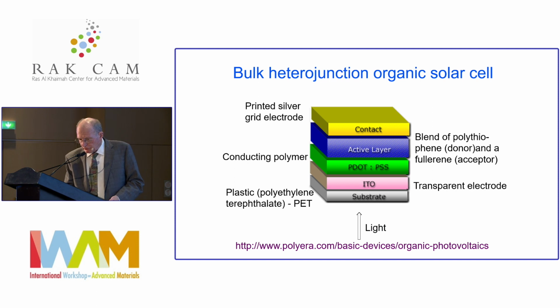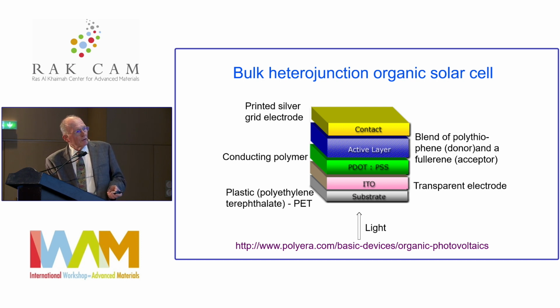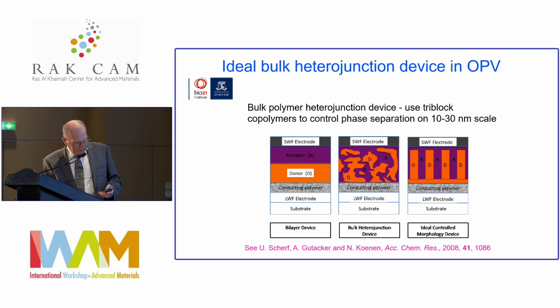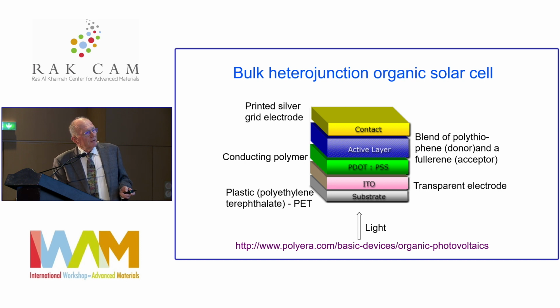Now, the bulk heterojunction solar cell has a typical configuration as illustrated on this slide. This is a simplified version, but you have a conducting positive contact anode, indium tin oxide, a conducting polymer, then the active layer, which in early devices was a blend of a donor polymer such as a polythiophene and an electron accepting material such as a fullerene, and then a top contact, which can be a variety of cathode materials, and silver is very common, because you can print a silver grid which is still transparent. Now, in the early days, people were getting about 2 or 3% efficiencies with this combination of materials.